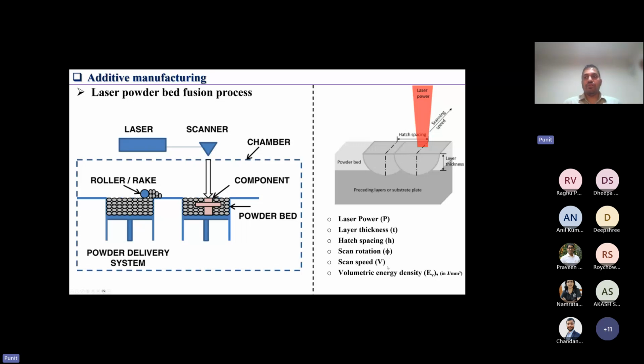There is also a parameter called volumetric energy density, and it is a combination of process parameters: laser power divided by layer thickness, hatch spacing, and scan speed. This has a unit of joule per millimeter cube, and it is usually used for reducing porosity or optimizing the density of the additively manufactured materials.